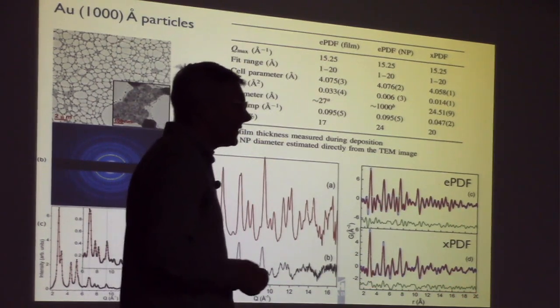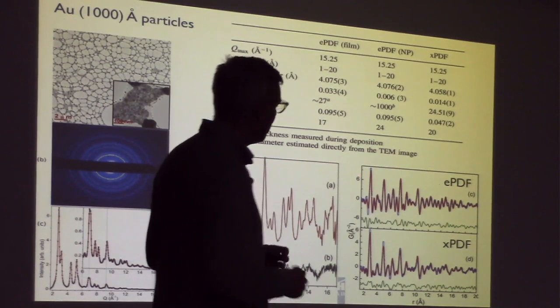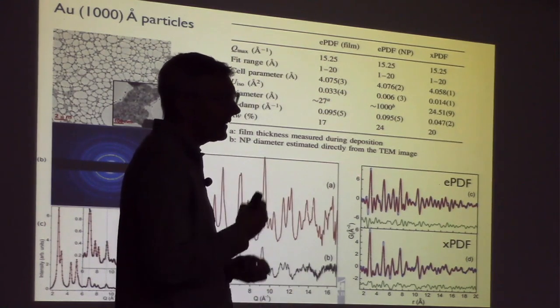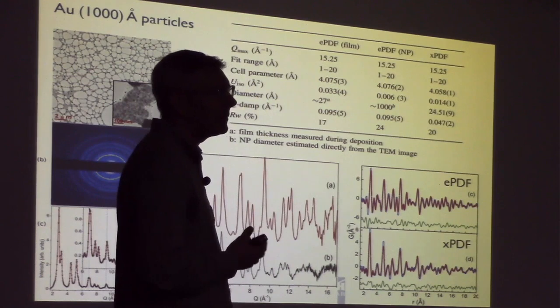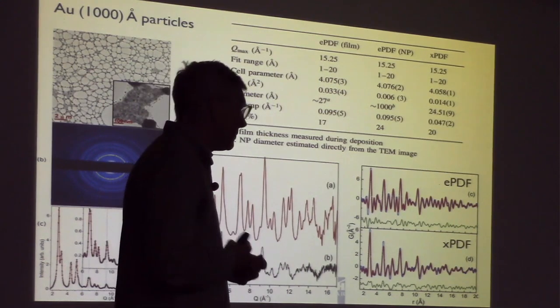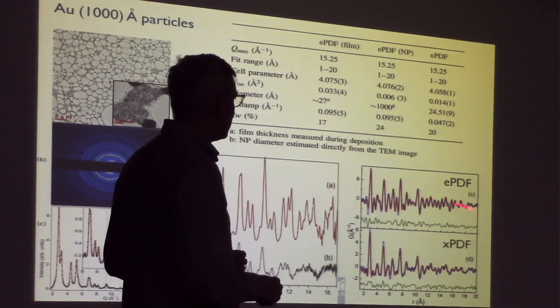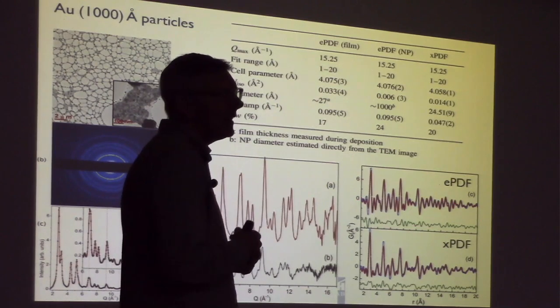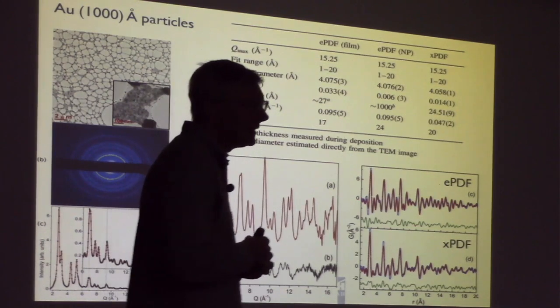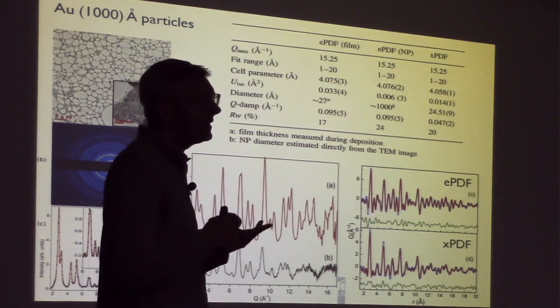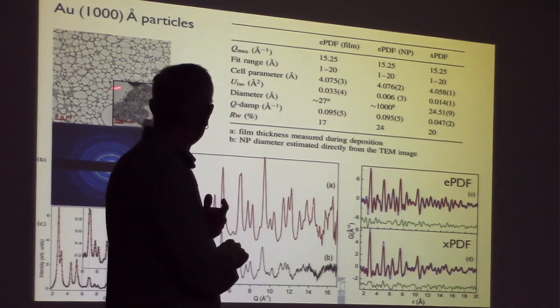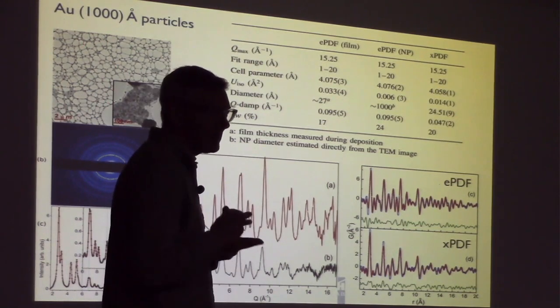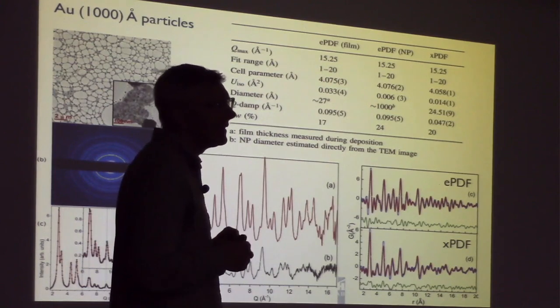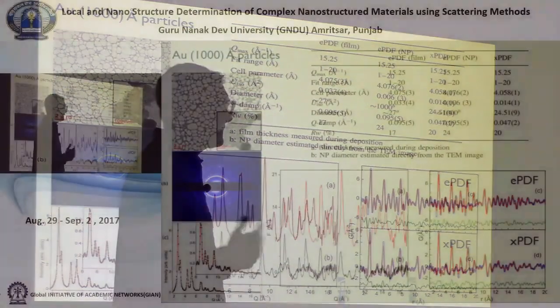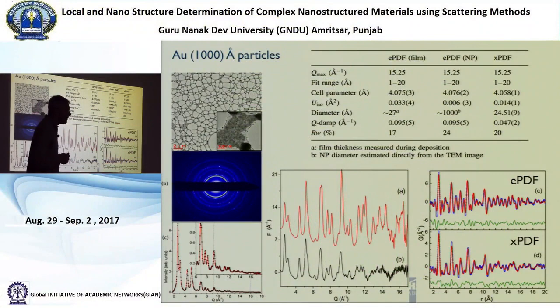So actually, there's a lot of issues with dynamical scattering. The electrons are very strongly interacting. You have to worry about dynamical scattering. But we can get actually pretty quantitative PDFs from the electron microscope. And that's actually very interesting for two reasons. One is that we can look at really nanograms of material, but the other is that actually a lot of university departments will have an electron microscope, whereas they won't necessarily have a synchrotron.